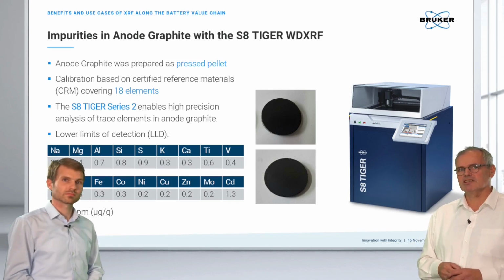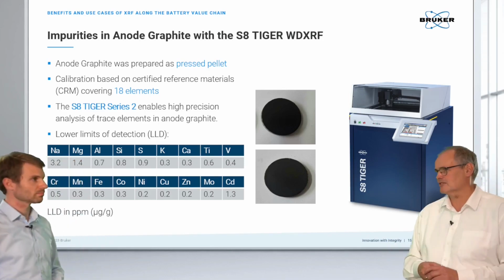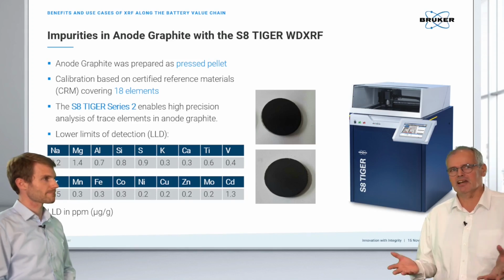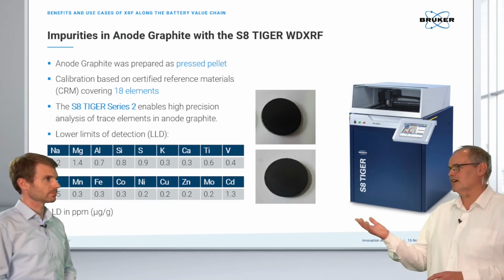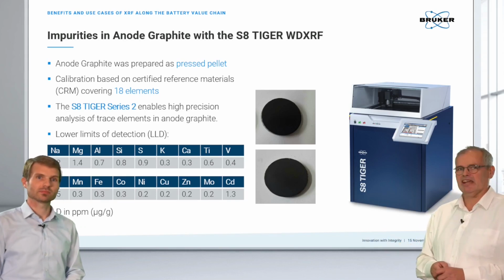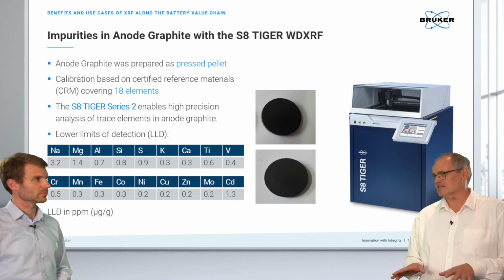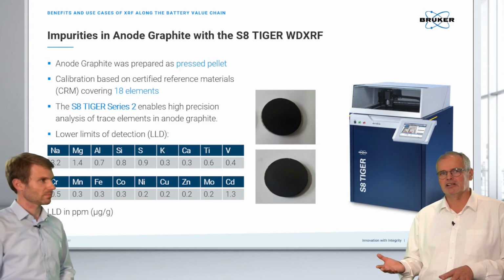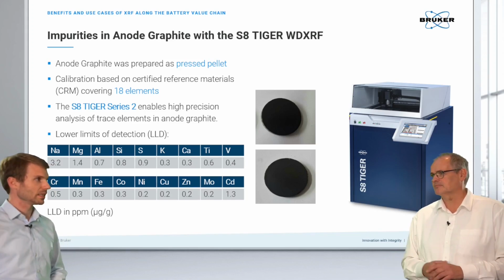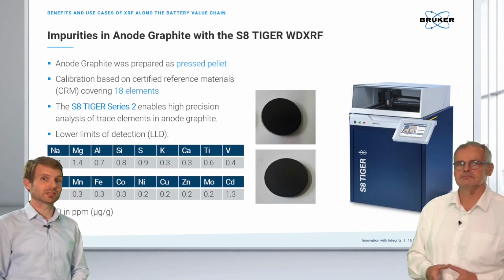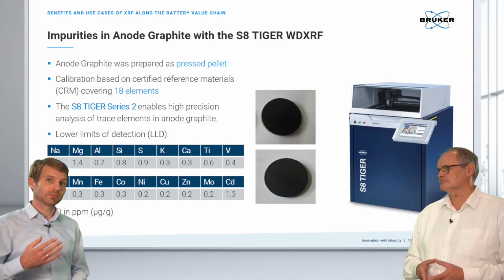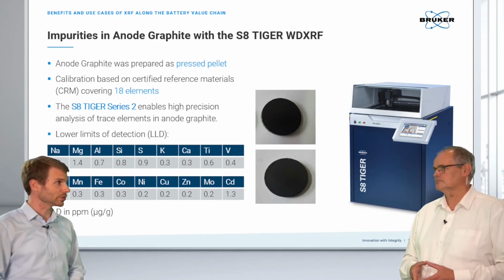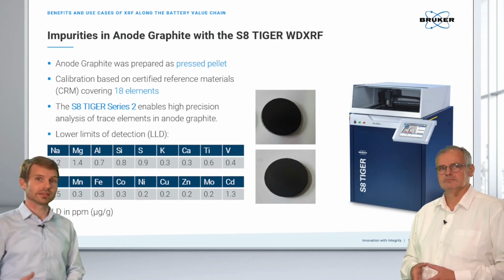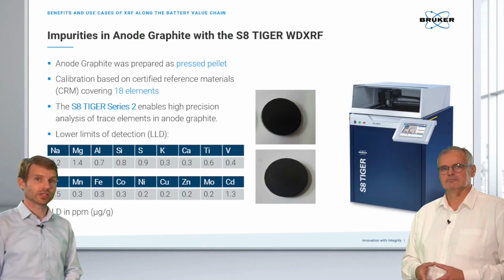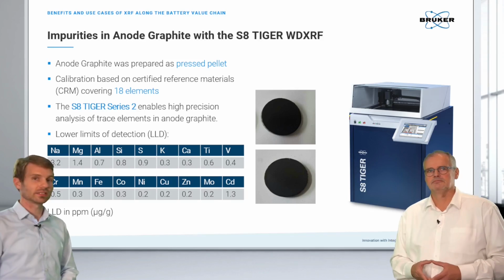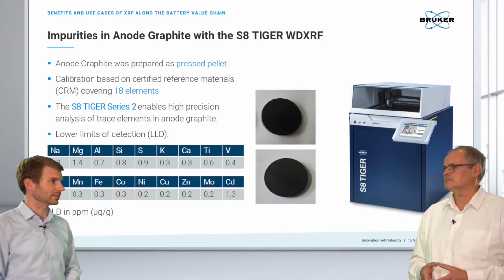You see here, it's very easy. We press the graphite powder with a little bit of wax into a pressed pellet, and then analyze and see directly cobalt starting from 0.3 ppm, which is excellent. So the purity can be easily assessed, and you can control whether the incoming material is according to spec or not. Some of these elements can really be quite dangerous when it comes to battery lifetime and battery safety, like sodium, which can cause overheating of the battery. So you really want to get to very low concentrations to ensure that your battery performance is right. And this also gives you the strength to really evaluate suppliers that provide your graphite.